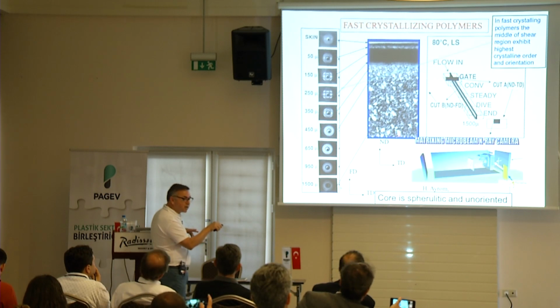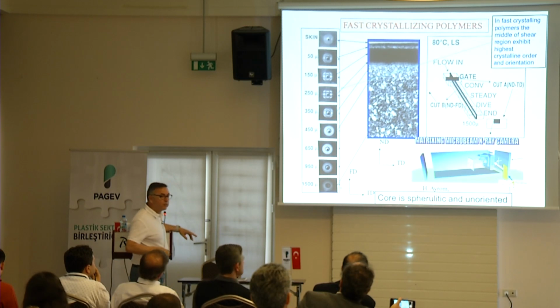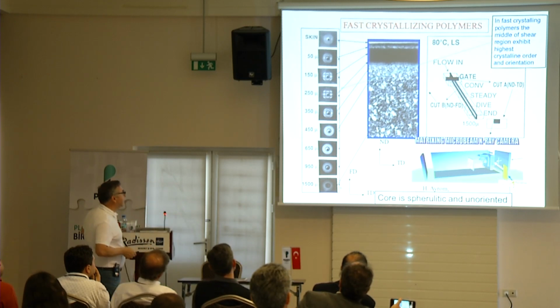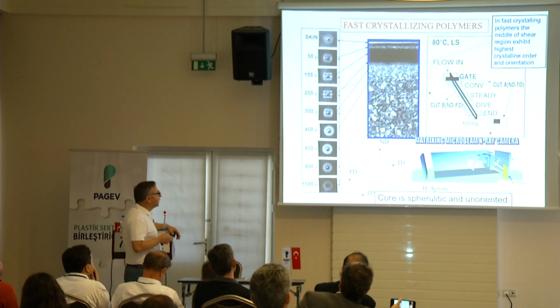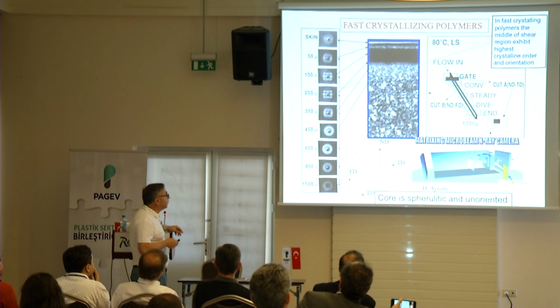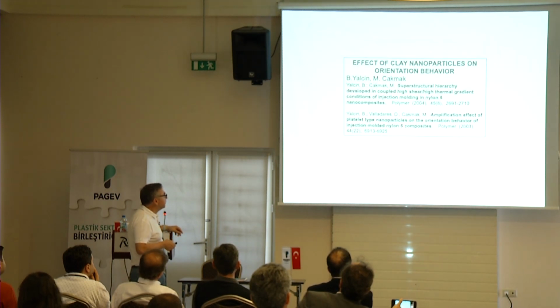These are large crystals. Following the thermal crystallization, what did we say? Closer to the skin, you have faster cooling. Here is slower cooling. Slower cooling means larger crystals. Faster cooling means smaller crystals. You see the gradient. That's typical for polypropylene and all similar materials: polyethylene, polypropylene, polyoxymethylene, and so on, and PVDF. All of them will exhibit one form or another of this kind of structure.